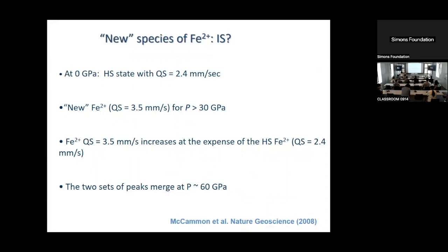Okay, my last question, I'm sorry to hold everybody up, is particularly as one gets away from totally dilute iron, if one gets to 25% or 15% or something. I understand the different spin states and different orbital states have different local octahedral volumes. And because the orbitals are involved, there is an anisotropic kind of Jahn-Teller thing. So that suggests that the different states may be coupled by a strain, which can propagate over longer distances. That's right. So is that coupling? That is the non-ideality that I mentioned.